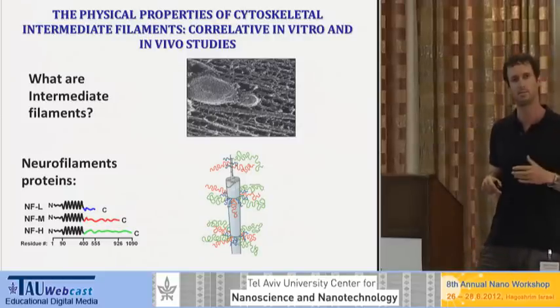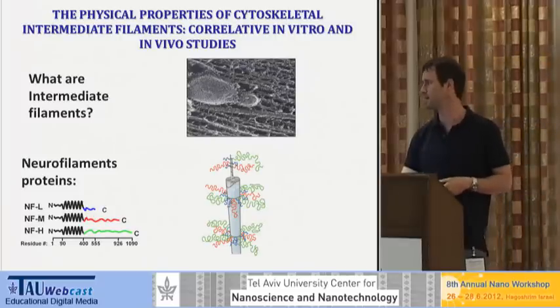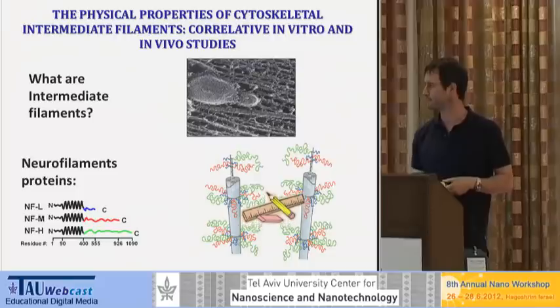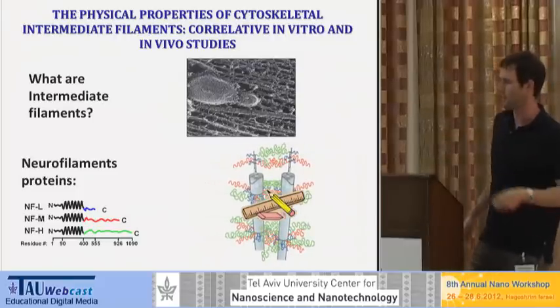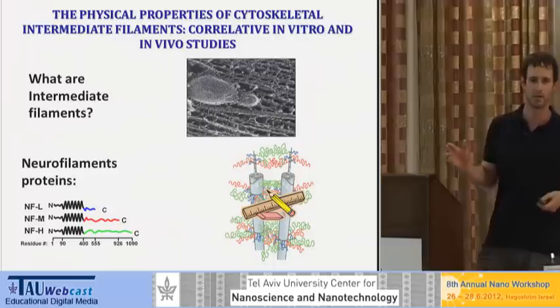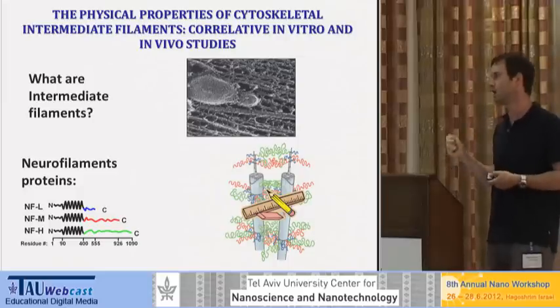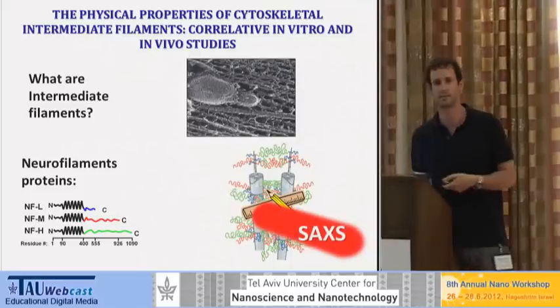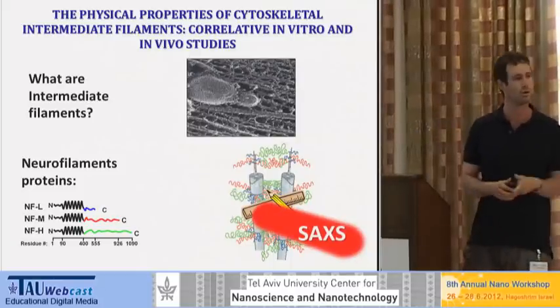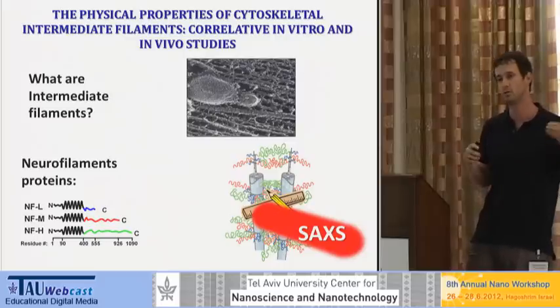Okay, what we are examining basically are the interactions dominating this self-assembly. We are measuring interfilamentous distances, and this is the ideal way of being able to study such interactions in biological systems. We're doing this using small-angle X-ray scattering. This allows us to do all of our studies without crystallization, without freezing anything. We can do this in solution.